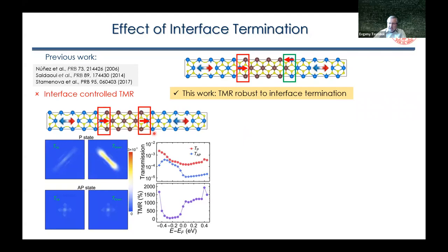So we change the termination in such a way that now for parallel aligned Néel vectors, we have parallel aligned magnetic moments at the interface. And we did a similar calculation of transmission. So we see some difference. Now we see for the parallel state some imbalance, some difference between up and down spin electrons. But still we have a very sizable difference between parallel and anti-parallel configurations, and the sign doesn't change. So everything is consistent more or less with what we found before, and even TMR may be higher as compared to the 500% I've mentioned before.